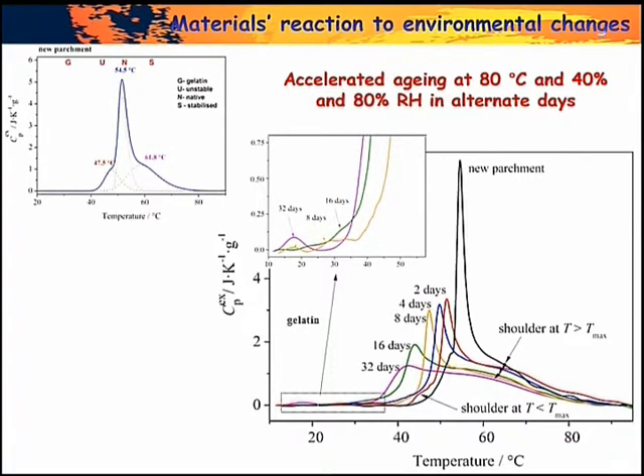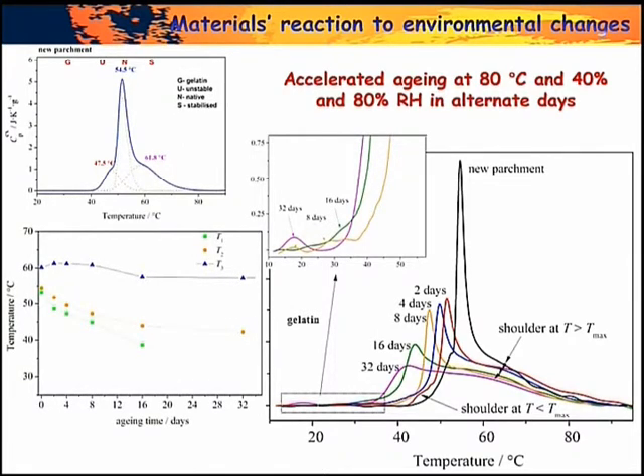Okay. This is a typical peak for a new parchment. As I told you, also new parchments present at least two or three collagen populations. The main collagen population we called native collagen population. This is the stabilized collagen population, and the presence of these two collagen populations is mainly due to the fabrication technology, and also a less stable collagen population. So how these collagen populations behave during aging, you can see in this figure. The temperature of the peak of the main peak, native collagen, tends to decrease. The same, the temperature of the unstable collagen decreases. Only the temperature of the stabilized collagen tends to withstand deterioration in these conditions.